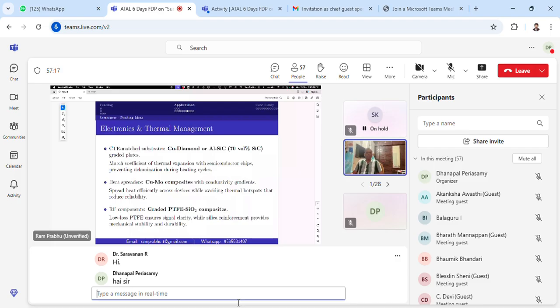Similarly, if you want a lighter weight one, you go for aluminum silicon carbide. Among all the ceramics, silicon carbide is the only ceramic which has a very high thermal conductivity. So when I integrate a lightweight material with a lightweight ceramic, I can derive a very lightweight structure which has a CTE matching with the semiconductor.